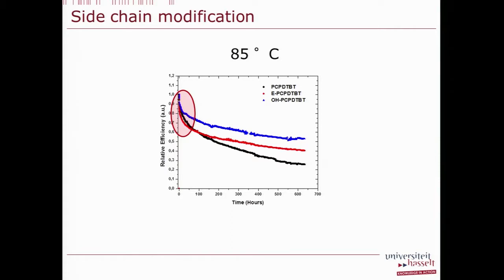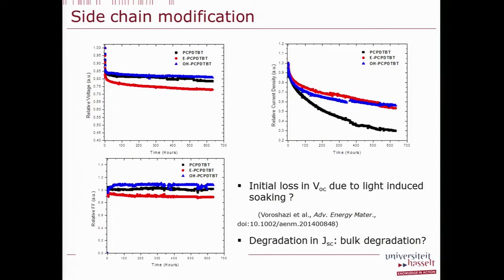Still, if you look at the initial part of the curve, there we also have this dramatic decrease. The question is, is this initial loss in VOC, for example, due to the light-induced soaking, as published recently by Voroshazi et al., and presented this morning in an excellent manner by Thomas Hümmüller, and the degradation in the short-circuit current, is this due to bulk degradation?